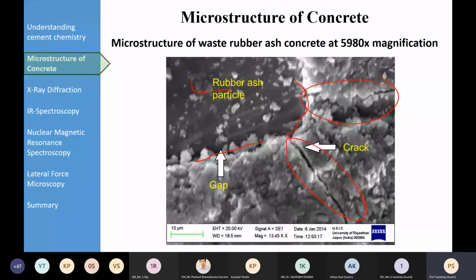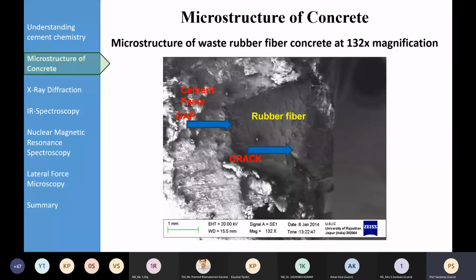concrete. So you can see here, at another magnification level, the rubber fiber, this time we used waste rubber fiber from tire. So when we use that, you can see it's clearly, distinctly visible. This is the rubber fiber, and this is the cement paste gap between the rubber fiber. And there's a crack within the rubber fiber also. So this crack in the rubber fiber will have its own effect on the ductility properties of the concrete and on the flexural strength, etc.